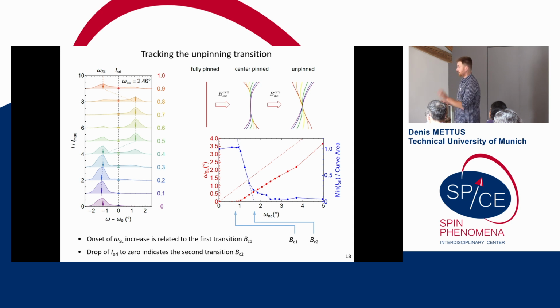In the rocking curve, any intensity corresponds to a part of the skyrmion phase volume which is looking in a given direction. So this value tells you how much of your skyrmion is still looking in the original field direction, and this part of the rocking curve tells you how much of your skyrmion phase is moving, following the field. In other words, this translates to the tails, and this translates to the center.